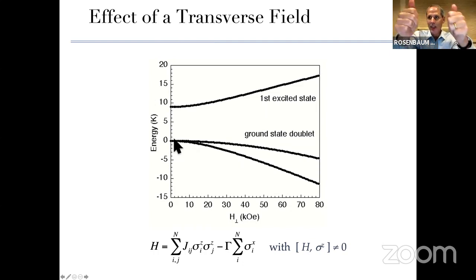However, if you put on a transverse field, remember I told you that the spins can't follow the transverse field to the Ising axis because of the crystal fields in the material. What it does is it mixes the ground state doublet with the first excited state and splits the ground state doublet. And now I have an admixture of spin up and spin down that's proportional to this knob that I have in the laboratory, this transverse field. Another way of talking about this, of course, is that the Hamiltonian, this is just the dipolar coupling, Jij, these are Pauli spin matrices, commutes with sigma z until you put on a transverse field. And once it no longer commutes, then of course you get quantum fluctuations that depend on the strength of the transverse field.